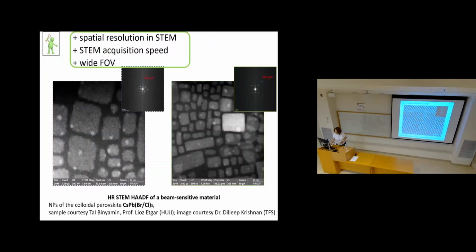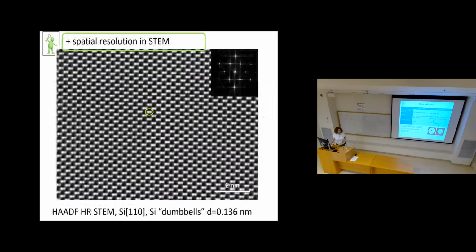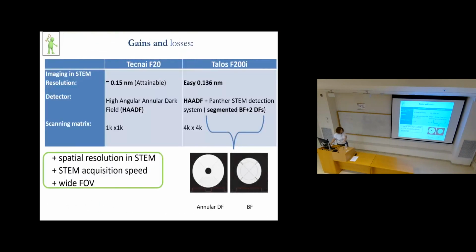Okay, so this is the gain in the resolution of the STEM imaging. The matrix available with STEM imaging is now 4K by 4K, the maximum matrix. That means that we have a wider field of view, as I mentioned in the TEM as well, and we have much more. Now we don't have only the only STEM detector with limited information, but we have a set